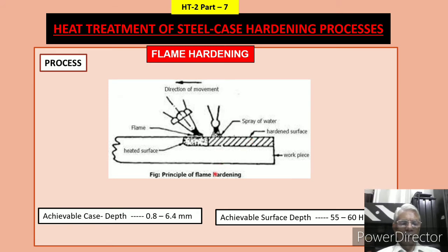Okay, and the achievable case depth with this is 0.8 to 6.4 millimeter, and the surface hardness which can be achieved is 55 to 60 HRC. Depending upon the composition of the steel, whether it is a highly alloyed steel or medium carbon steel, you can achieve a hardness up to 55 to 60 HRC. So this is how this process works. Now, I will tell you the different methods.